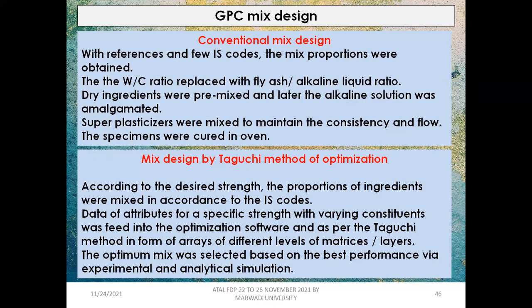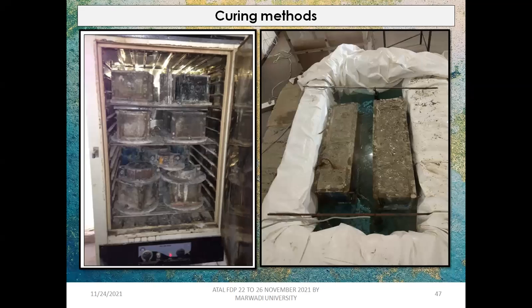So we tried with that, and we could definitely reduce the trial and errors to an extent. You don't need to actually create all the mixes and keep on casting everything together and waiting for the results to come. You can go for a single-line mixture, which is already optimized by the Taguchi method itself, and you can confirm that particular prediction with the help of experimental results.